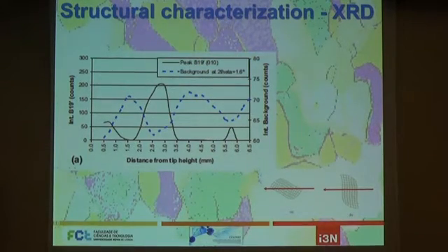And we clearly identified this geometrical feature in the way the intensity of the martensite peak varies versus the intensity of the background of the diffraction pattern that we took. You see that when the background goes high, that means we are looking through the thinner part of this cross-section, and when it goes high we have practically no martensite intensity peaks. And when the background goes down, we have a high intensity of the martensite peak.